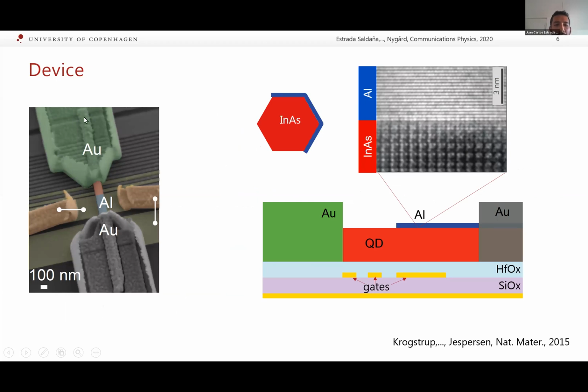And the aluminum has been etched on the top part of the nanowire. And then the nanowire has been contacted with two titanium-gold leads. And this forms a normal metal-nanowire-aluminum junction.